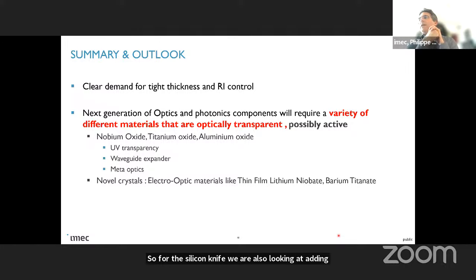In the world of optics, clearly we are relying on the refractive index contrast. So you need to be able to deposit these thicknesses very uniformly. You need to be able to pattern them. We are talking about pillar technology. So it is very common that you need to have several hundred nanometers of layer thickness and sub-100 nanometer pillars. Depositing the layer and being able to etch it is very important. And then you have the next step, which is you need to put oxide, the lowest index material. You need to be able to do gap fill.